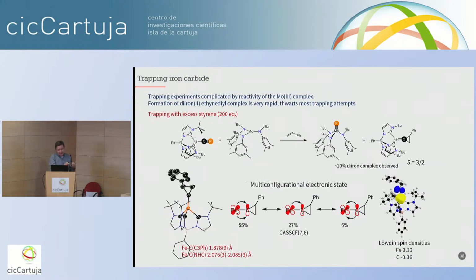We were not satisfied with that because maybe we've sort of convinced ourselves what's going on, and that's not correct. So we tried very hard to trap this, and finally we found with styrene we could actually trap the carbide. So we actually do the reaction in styrene as a solvent. So you mix these two in styrene, we again make the carbide, and then we could isolate this carbene complex here that's formed from the carbide. We still get a little bit of the diacetylide compound. So here's the crystal structure of this complex here.